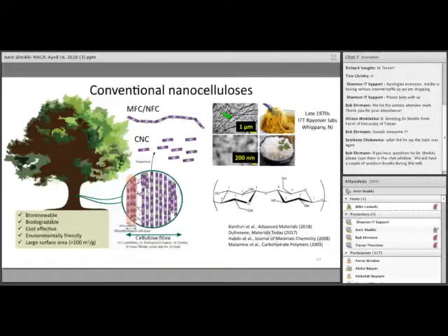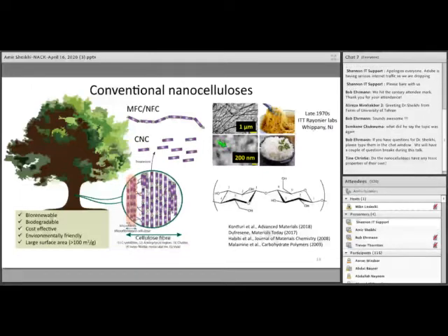This aggregated and bundled structure of these fibers, and cellulose nanocrystals remind us of rice grains, these nano needle shape particles, a couple of 100 nanometer long and a few nanometer thick. And of course, I don't need to mention that all these materials are made of cellulose with these glucose-like units with reducing ends and non-reducing ends. The benefit of these materials is that they are biorenewable, they're biodegradable, they're cost-effective, environmentally friendly, and they have a very large surface area, enabling us to use them for a range of applications. And let me show you what happens if you increase the concentration of these materials. You form a physical gel, as I show here.